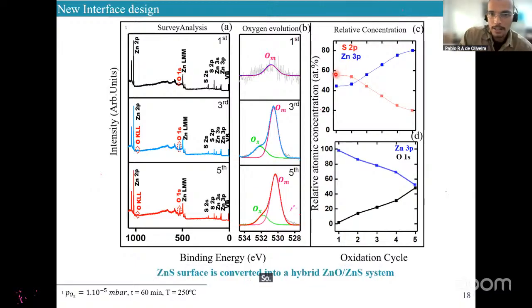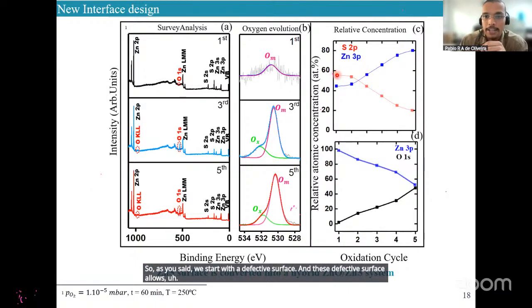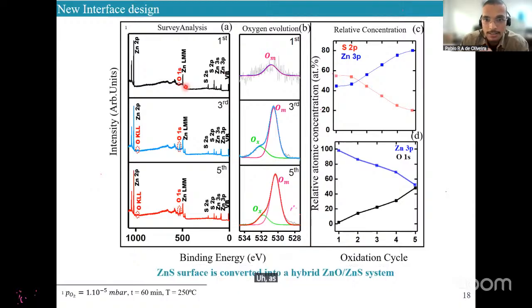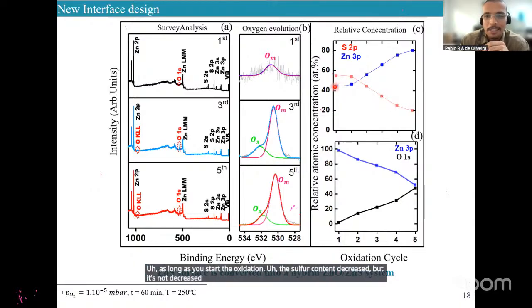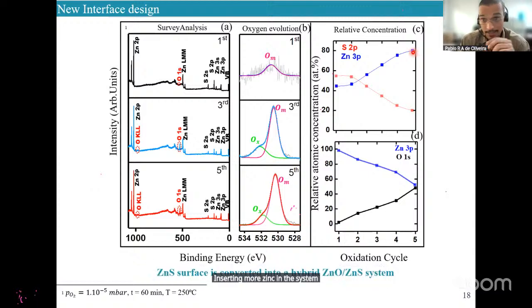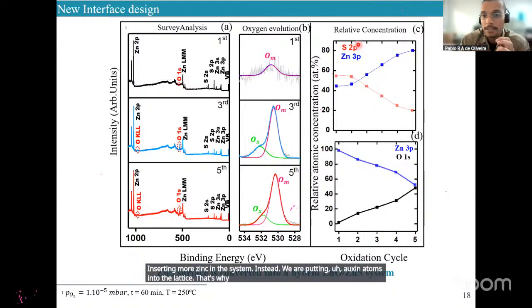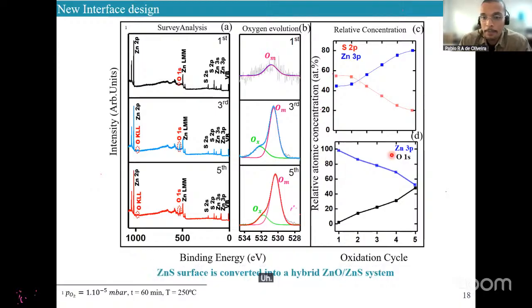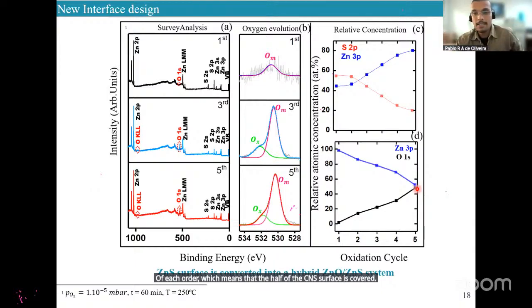As you said, we start with a defective surface, and this defective surface allows the oxygen reaction to take place. As you start the oxidation, the sulfur content decreases, but it's not decreasing because we are inserting more zinc in the system. Instead, we are putting oxygen atoms into the lattice. That's why the signal of sulfur is mitigated. Interestingly, when you compare the zinc signal against the oxygen signal, we can note that at the last cycle, it reached almost half of each, which means that half of the ZnS surface is covered by ZnO.